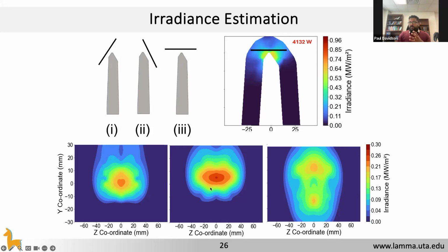And this is what the flux profile looks like. When I first saw it, it reminded me of a Rorschach test, but this is quite interesting. You can see that, depending on the facet and the location of the plate itself, you get a very nonlinear distribution of the irradiance. So the question was, can we replicate this and measure the temperature both numerically and experimentally?